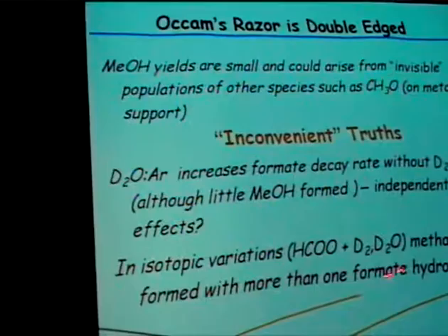There's some extra hydrogen we can't account for, right? And you can postulate as well as I can what the source of that is. It could be a minority pool of that sort of H. It could be some minor methoxy that we cannot see that's also being cleansed at the same rate. And right now, we really don't know. That's what I'm here to tell you.